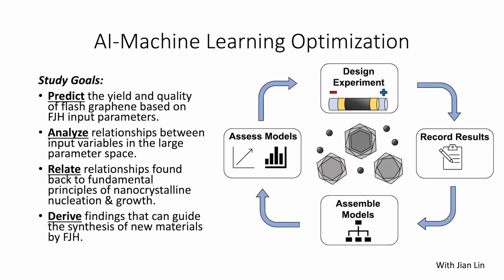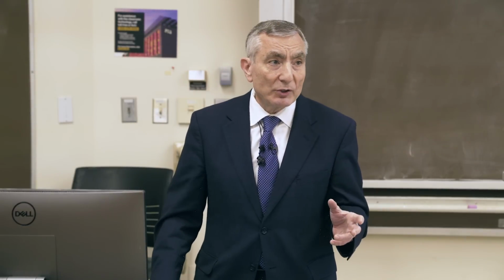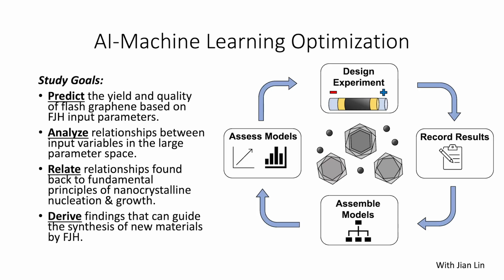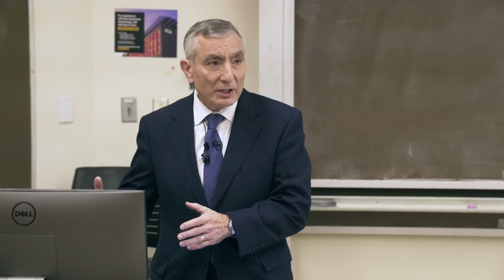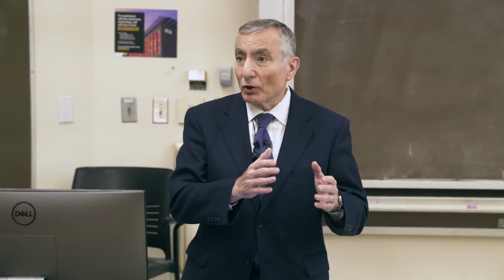So if you have a high carbon source like coal, metallurgical coke is a coal product. It's the material that's used to make aluminum, where you have a sacrificial electrode. And what you can do by building these sort of systems is when you have that level of carbon, it's 90% carbon, you can get 90% yield of graphene. In other words, if you start with a kilo of metallurgical coke, you'll get 900 grams of graphene out of this, where almost all the material in there is graphene. You can only get 90% yield because it was only 90% carbon to start with. If you start, like I said, with carbohydrates, your yield is lower, but your carbon yield is still very high. It depends on how much carbon you have going into the system.